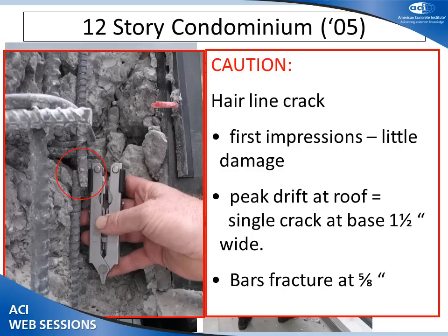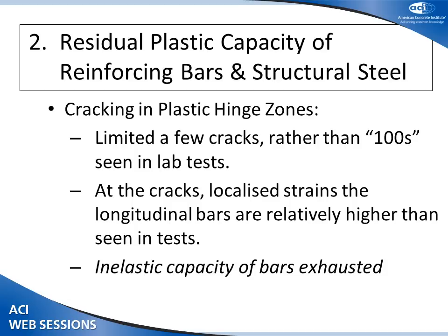We found that the peak drifts at the roof led to that single crack at the base of the wall opening up about 1.5 inches. And we know that these sorts of bars fracture at 5/8 of an inch, so they didn't have a show of surviving. The next question, following on from this, is what is the residual plastic capacity of our reinforcing bars and our structural steel? As I've mentioned earlier, we're not getting thousands of flexure-shear cracks. We're only getting 2, 3 or 4 cracks where all the deformation is concentrated. The other factor is that there are very, very high localized strains in the bars either side of those small numbers of cracks.